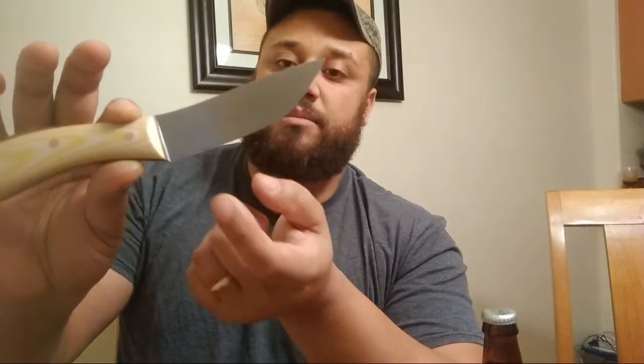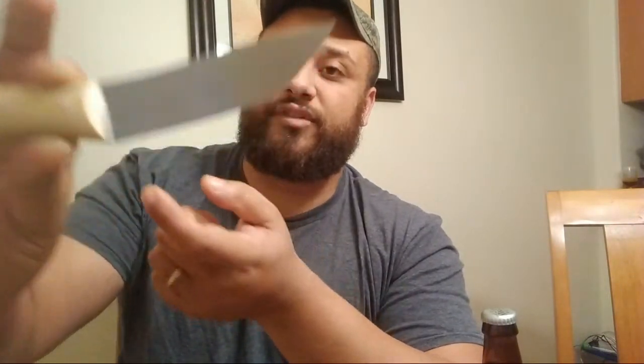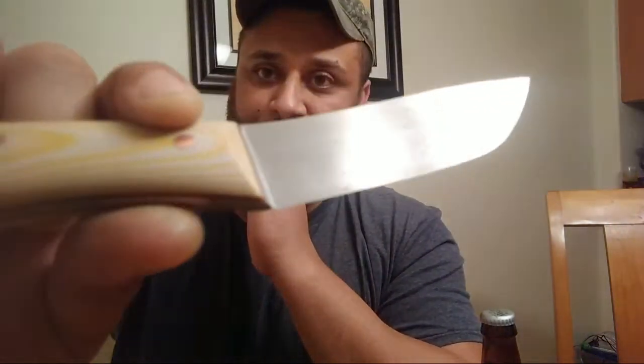You can take a knife in AEB-L, which should be easy to grind and make a knife out of, and put it at 30 thou behind the edge, 15 degrees per side, with a bevel about that wide. And you could take my Rex 121 at 70.5 HRC, 32% carbide volume, and I'm about 6 thou behind the edge. My edge at 15 degrees per side, can you see it?